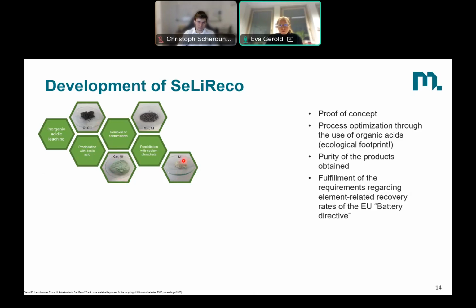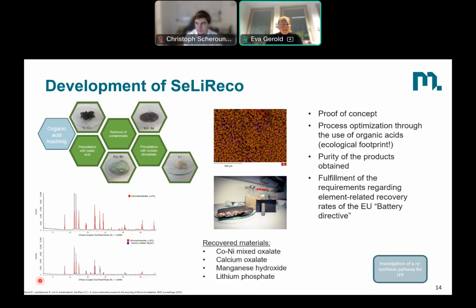What we have seen there is that the purity of the products obtained is fine for getting back to batteries, so for PCAM production. We could fulfill all the requirements from the EU battery directive with this process, but what we have seen also is that there is quite a high CO2 footprint for the inorganic acidic leaching, because sulfuric acid actually has quite a high footprint. And that was the first thing why we started studying organic acid leaching. And we've seen that this process option is also working, that we also can recover quite high quality products. And what we also have seen is that we can do resynthesis of PCAM with these products, for example, LFP.